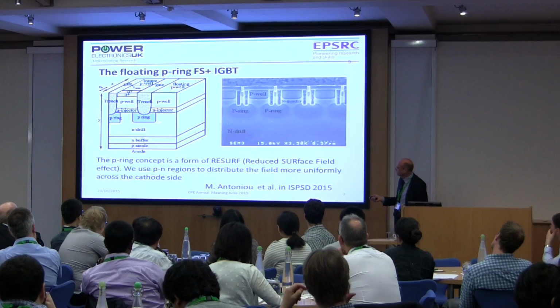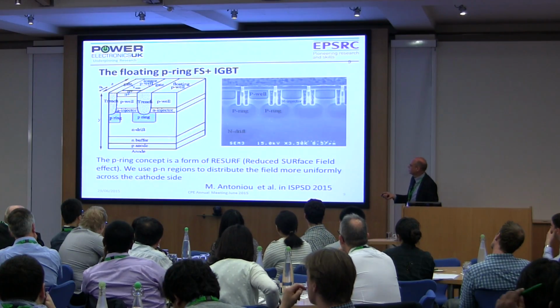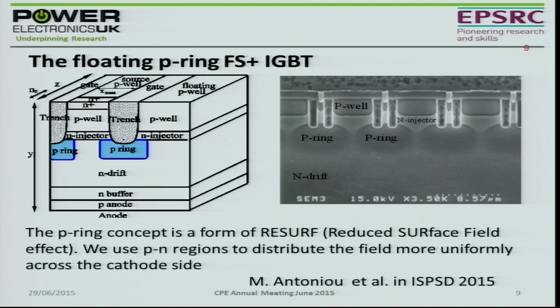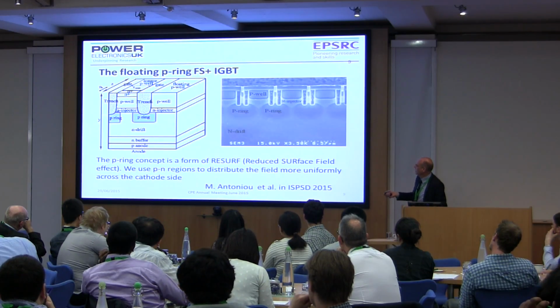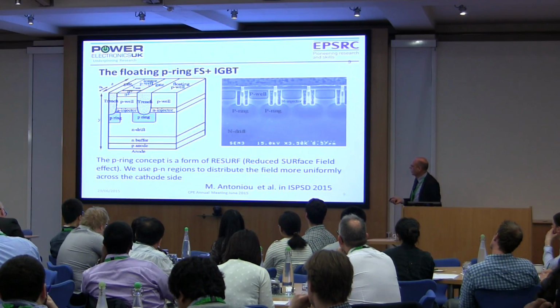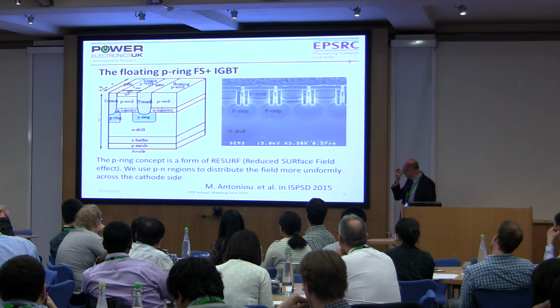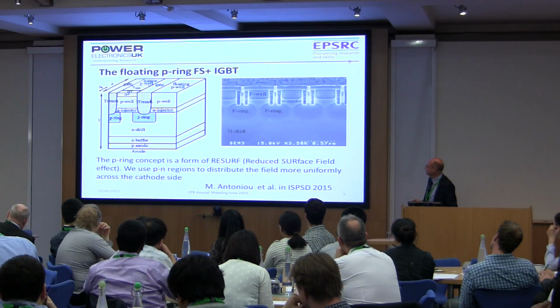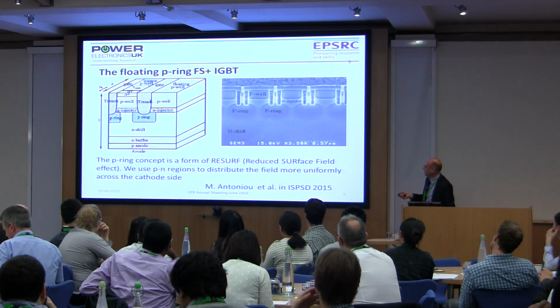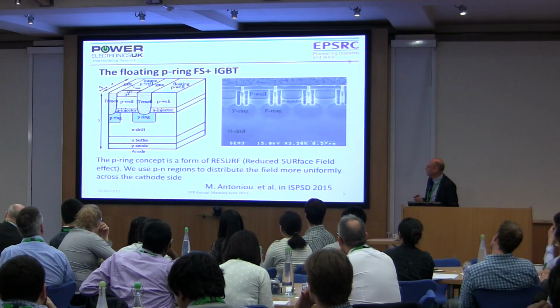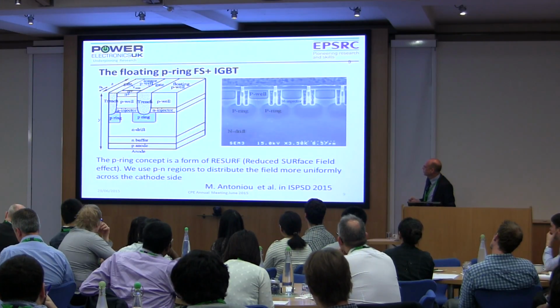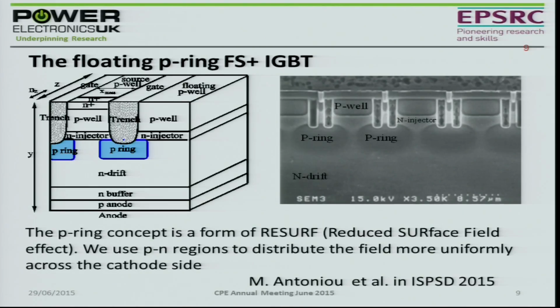Now, the superjunction part of it is enabled by these P-rings here at the bottom of the trenches. Normally these trenches would have a P implant at the bottom anyway, but these have been extended and made bigger so that you can see you've got a sort of superjunction structure here. You've got an N-type region here and then these P-rings partially penetrating the depth of the drift region. And so these act as charge compensation parts of the structure. They make what's called a RESURF structure, reduced surface field, as they would in a lateral device. And that allows you to increase the doping in this drift region as well. So this whole structure becomes a very effective and one of the most advanced forms of IGBT, certainly in the engineering of the top part of the surface that you can get.